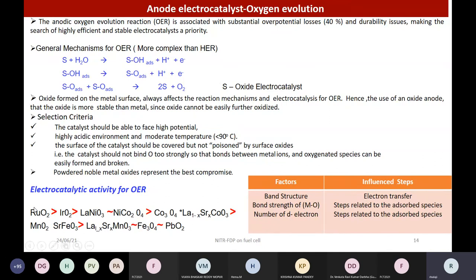If you see the electrocatalytic activity range for this OER, ruthenium oxide is better than iridium oxide, but people will not use ruthenium oxide alone for the anode electrocatalyst. Ruthenium oxide is in the plus 4 oxidation state. When you operate the system at high potential, the ruthenium has the tendency to go further, from the plus 4 oxidation state up to plus 8. So over a period of time, it has a tendency to undergo further oxidation and lead to ruthenium leaching from the electrocatalyst. That's why it is not advisable to use ruthenium oxide alone, though it has very good anodic electrocatalytic activity for the oxygen evolution.